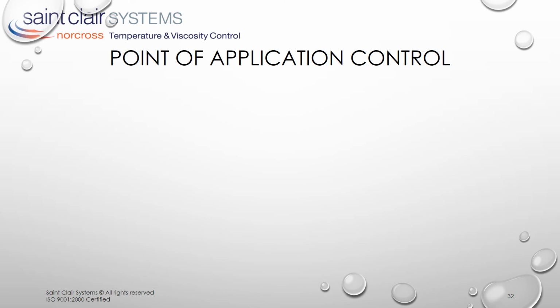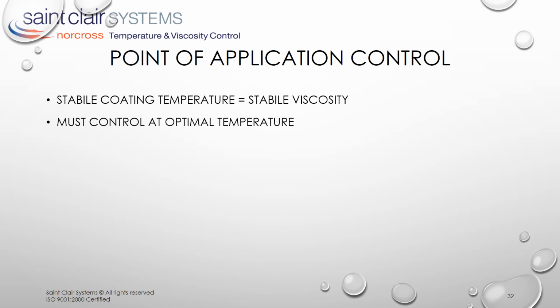In each of these cases, it is clear that stabilizing the process requires controlling the temperature of the coating at the point of use. Though the approach for each is unique, the end result is the same. Stabilizing the coating temperature stabilizes its viscosity and helps us to bring the process under control. It is just as important to control the temperature at the optimal value. Often, with modern coatings, that optimal value is in the middle of the ambient temperature range. In many cases, and in many climates, it is necessary to heat the coating during the cool morning hours and cool it through the warmth of the afternoon. Seasonal temperature variations are generally even more extreme, accentuating these requirements.